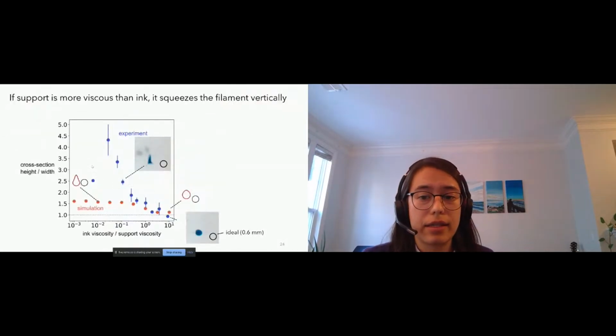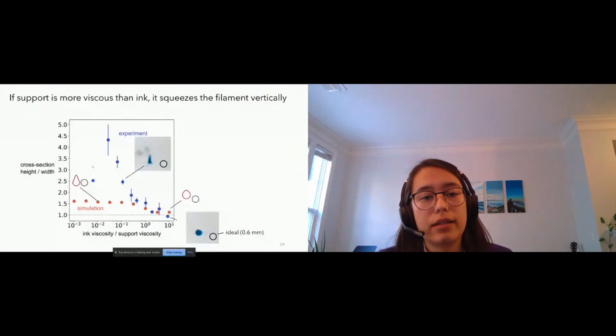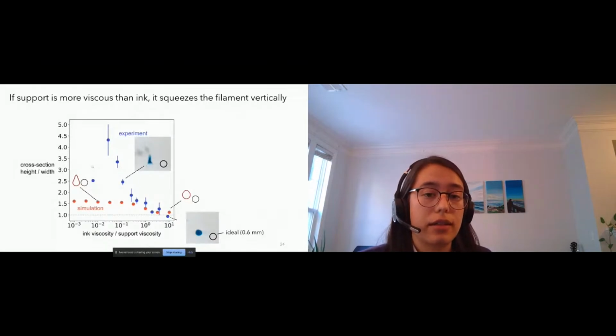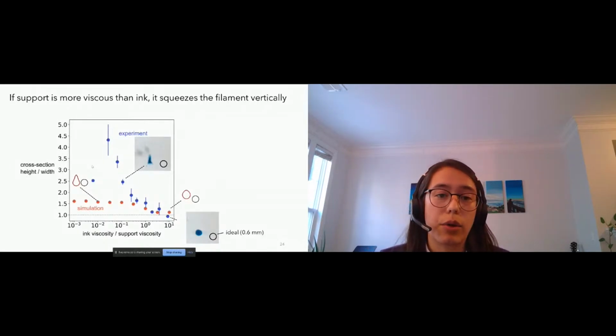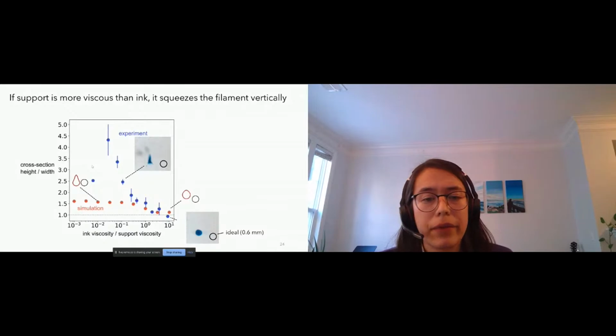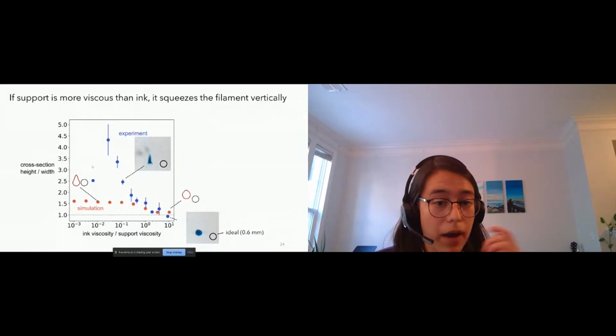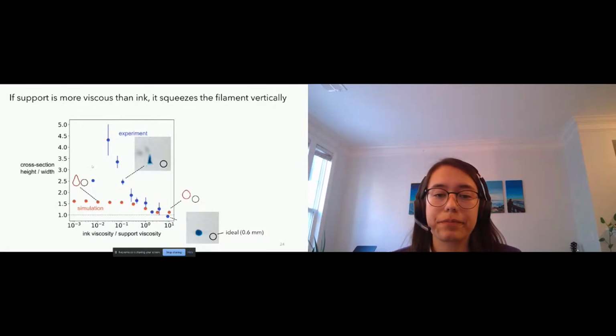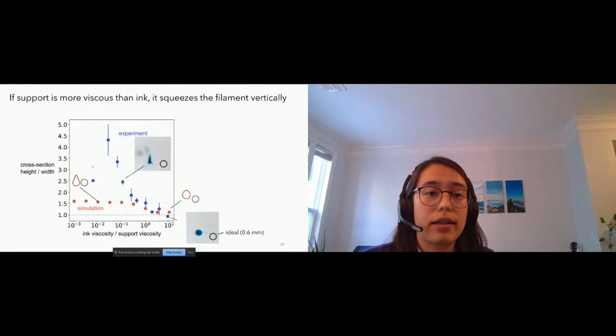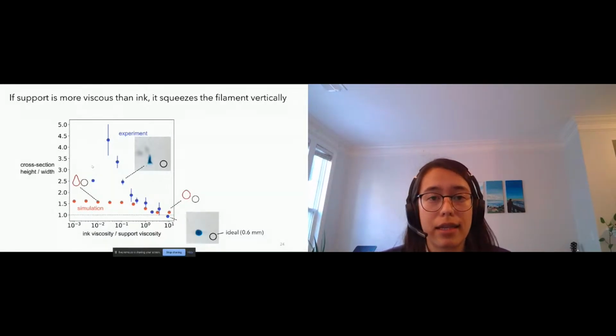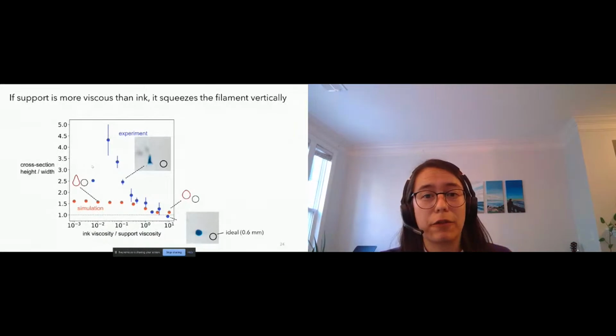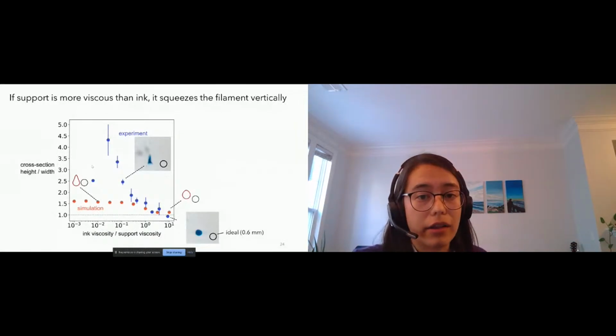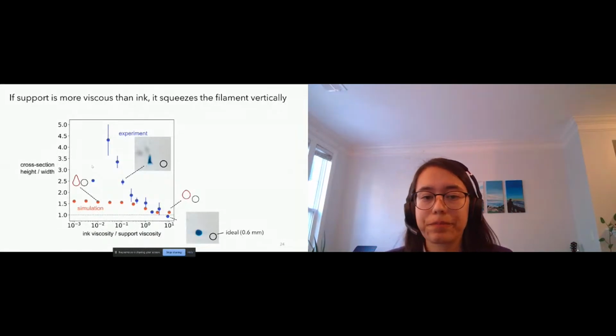So here, what you can see is that as you increase your viscosity ratio, you decrease the cross-section height of a filament. That occurs in both our simulations and our experiments. And there's pretty good agreement as we go to higher viscosity ratios. So what this tells us is that if the support is more viscous than the ink, it just ends up squeezing the filament vertically and creating these very tall and narrow aspect ratios.